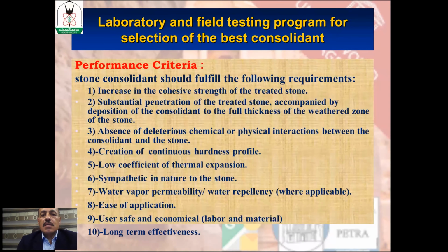And then we conducted a laboratory and field testing program for the selection of the best consolidant to be used in our future conservation plan. As I mentioned, stone decay is really serious in the stone blocks of Qasr al-Bint, and replacement of these stone blocks is not an option because of the value and significance of this important monument. We have to keep the authenticity of the monument as much as we can. So a proper consolidant is badly needed.